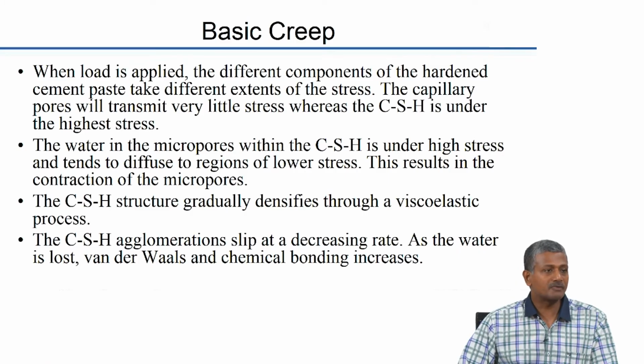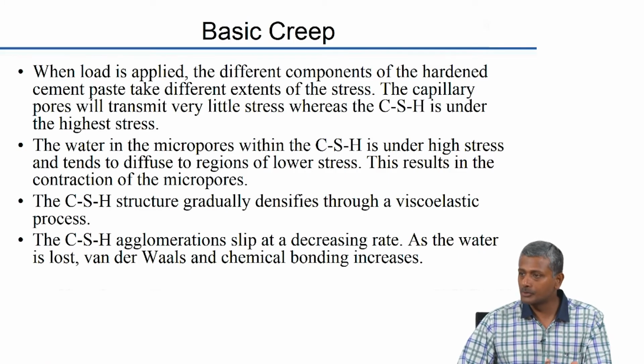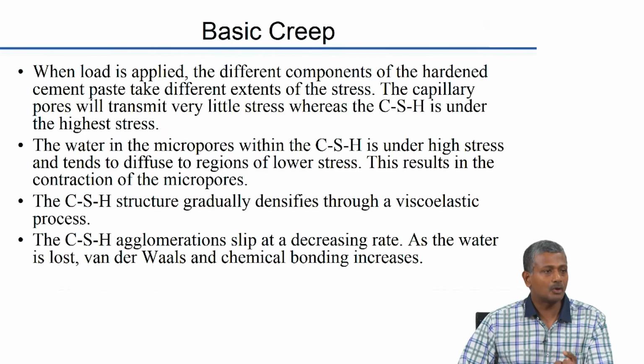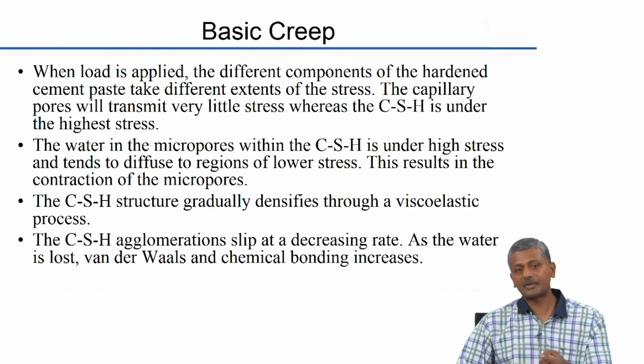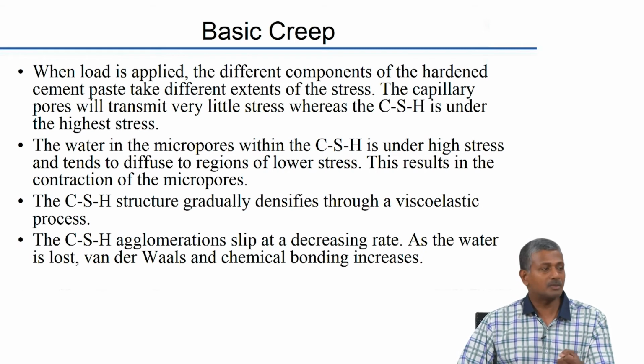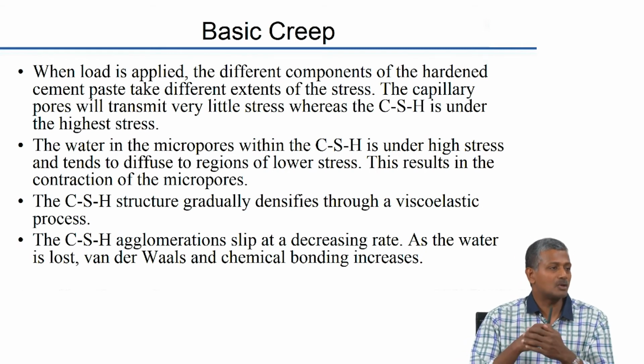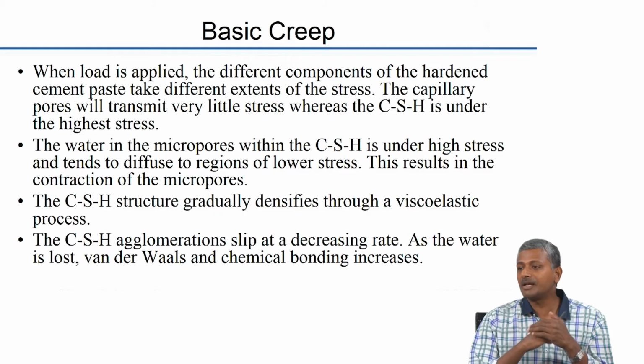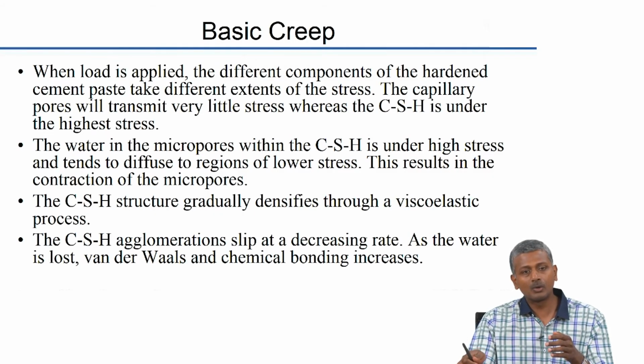The capillary pores, obviously being almost capable of taking no stress, will not take much of the stress, but CSH being the strongest component will take the maximum level of the stress. So, water in the micropores or the interlayer and adsorbed water in the CSH is under very high levels of stress. So, it starts getting dissipated towards the lower stress regions like the capillary pores, for instance.